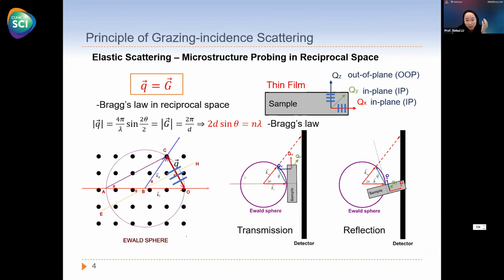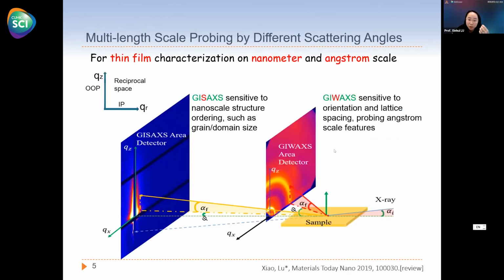So once our incident beam and detector are fixed, this Q is fixed. So to probe different orientations of the structure, we have to rotate our sample into this reflection geometry so that this Q can have both Qz and Qr components to understand the out-of-plane and in-plane structure inside the thin film. Then to understand the multi-length scale structure, we basically just move our detector away from the sample. When it is close to the sample, we are collecting wide angle scattering, which corresponds to small features, angstrom level features. We call this GIWAXS. And if we move our detector far away from our sample, we are collecting small angle scattering, which corresponds to larger scale, nanometer scale structure.